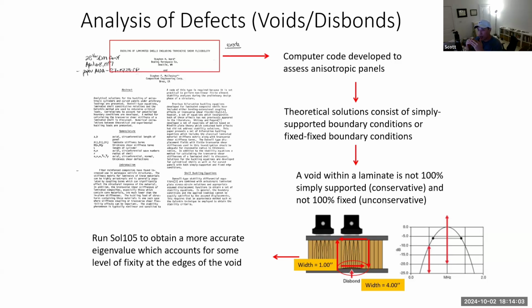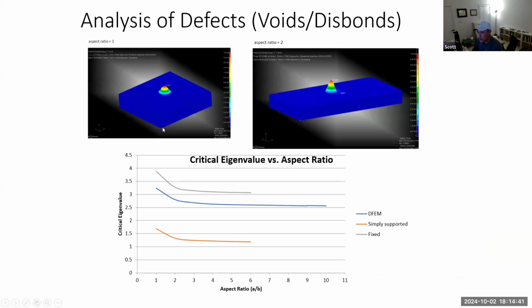Because imagine you have a panel, right? The face sheet, like down here, is no longer supported by the core, right? So now that face sheet that's disbonded in a local area will be more prone to buckle out, because your buckling length has grown, since it's no longer supported by the core because the adhesive is not bonding that face sheet to the core. So that area can possibly buckle. That's something that we've got to check. Typically you can use this closed form solution, but I don't like to typically do that. What we typically do to get the most realistic answers is model it in a FEM.